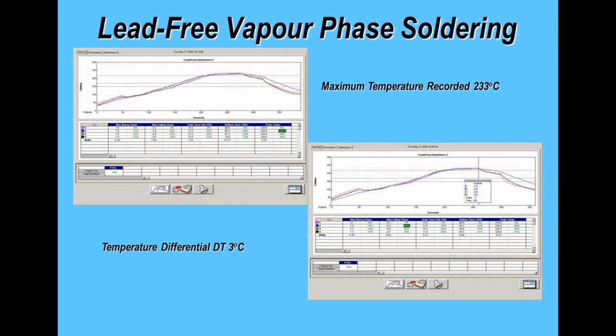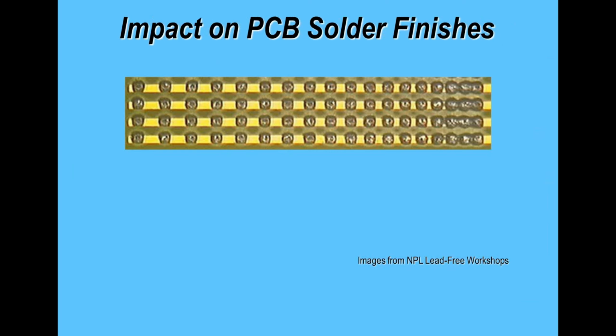Now, again, remember, if you monitor positions on a board with thermocouples, if you monitor positions which are radically different, you'll get a radically different result. If you monitor positions which are very similar in thermal mass, then you're going to get a very similar result. So again, it's easy to fool people by using the wrong monitoring position. With vapor phase, because the consistency of heat up and cool down is far tighter than a convection oven, then the actual result you're seeing is perhaps more meaningful. We'll come back to that a little bit later on.